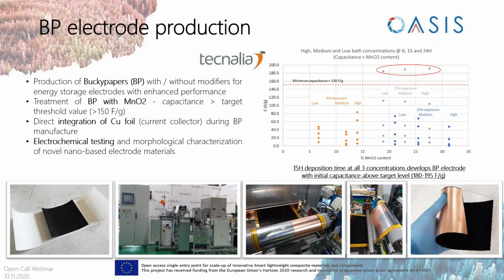As can be seen from the diagram on the right, the optimum deposition time appears to be 15 hours, since it develops a Bucky paper electrode with initial capacitance above the target level. So up to now, a 30% increase in capacitance has been achieved, which corresponds to 180 farad per gram.